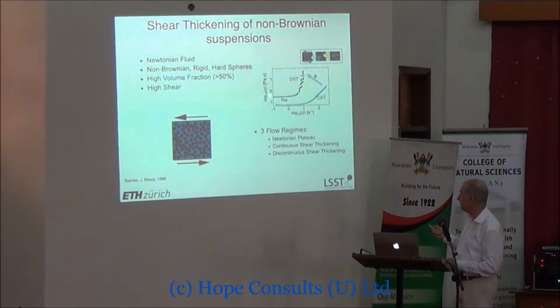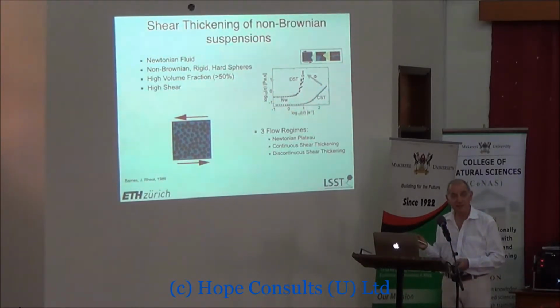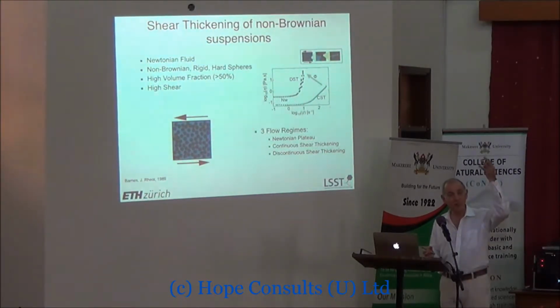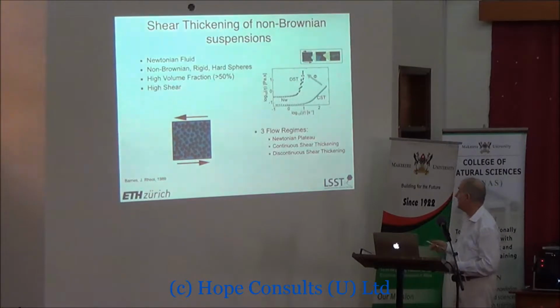What is a real problem for them is if they get what's called discontinuous shear thickening, which is where they get to a certain point and the viscosity increases to infinity. If it increases to infinity, then you just destroy the pump. And you can imagine what happens if you destroy the pump when you have a column of cement which is hardening sitting above it. This is a disaster, and they really want to understand this, and they really want to avoid this. So this is a Newtonian flow region, this is continuous shear thickening, this is discontinuous shear thickening.